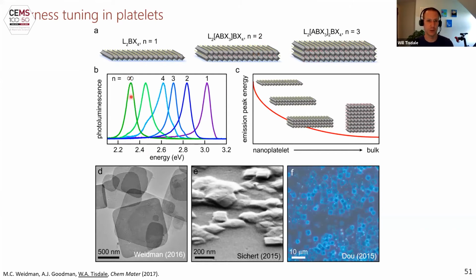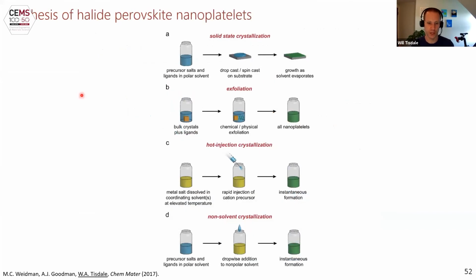And you can see in the photoluminescence spectrum that for the bulk lead bromide system, it emits in the green. And then as you reduce the number of lead halide layers down to just 4, 3, 2, 1, you get quantum confinement and a blue shifting of the emission spectrum toward the ultraviolet. There are a number of ways to make these materials at this point. The way that we make them in my group is what is most often referred to as a ligand-assisted re-precipitation.